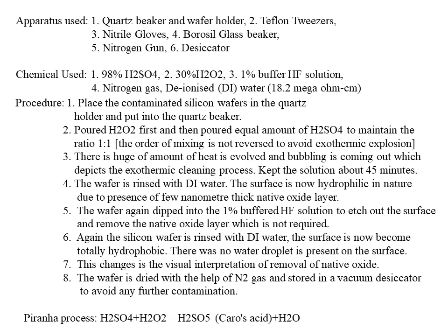That means after the Piranha cleaning, the wafer is hydrophilic, and after the HF cleaning, the wafer becomes hydrophobic. The change from hydrophilic to hydrophobic symbolizes that there is no native oxide present over the silicon wafer, and this is a visual examination process. That means we have etched out the entire native oxide layer over the surface.